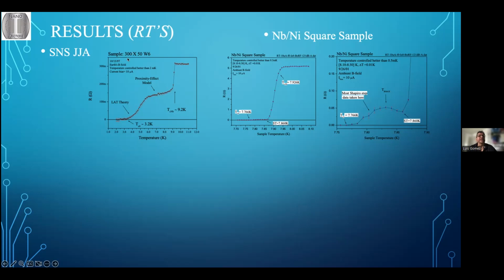There are 300 crosses along the current direction, and 50 crosses parallel to that. So there are 300 in series, and then 50 columns of those crosses. This is what is called the 300 by 50. As you go down in temperature, you get a value which doesn't change with temperature. Basically, it is the resistance of the whole system, including the gold underneath. Gold is a normal metal, so below a certain temperature you just get a remnant resistance that doesn't change with temperature. But then all of a sudden, each one of the crosses starts becoming superconducting, right at 7.2 kelvins. This is the transition temperature of the niobium.